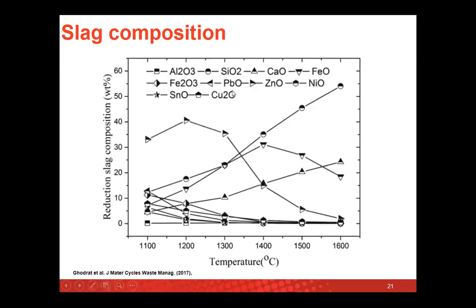So slag composition, you can see we modeled between 1100 to 1600 degrees centigrade. For example, at 1100 degrees centigrade, if I just talk about zinc oxide, zinc oxide is coming about 30%. But if you increase the temperature to 1600 degrees centigrade, the zinc will be vaporized. It becomes volatile, because zinc is not stable at higher temperatures. So zinc oxide will go off as gases. Similarly, this is related to the silicon oxide. Okay, so the silicon oxide component is less at low temperature, but at a higher temperature, this component will keep on increasing. This is also related with the oxidation steps as well. Similarly, some other slag phases that we have, iron oxide, silicon oxide, calcium oxide, and some alumina, their composition will change as we change and increase the temperature.